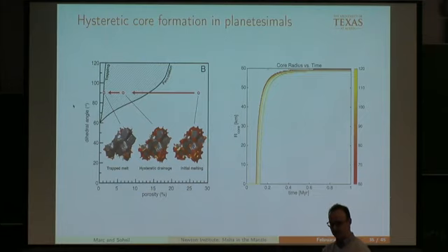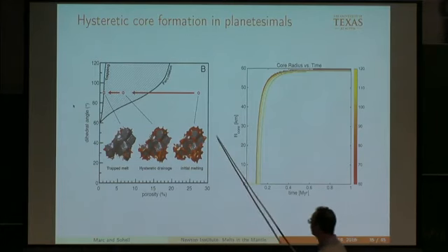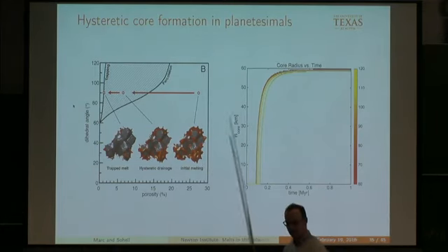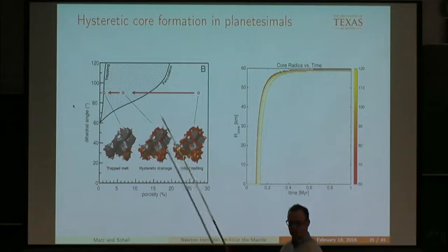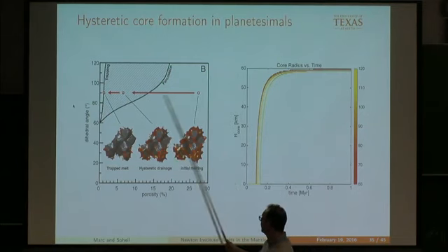Well, the meteorite shows that there are samples where the obvious thing happens: you melt all the stuff that melts early and you have 30% porosity. If that's what happens, then you create a connected pore network, totally irrespective of the dihedral angle. And because there's hysteresis in the network topology, you can drain it way past the percolation threshold.